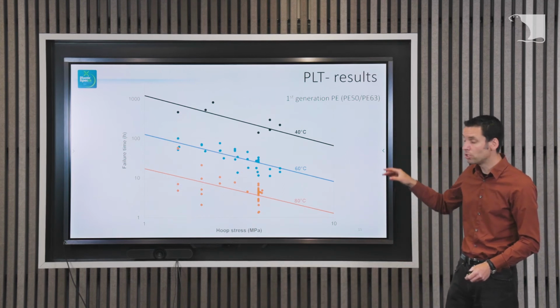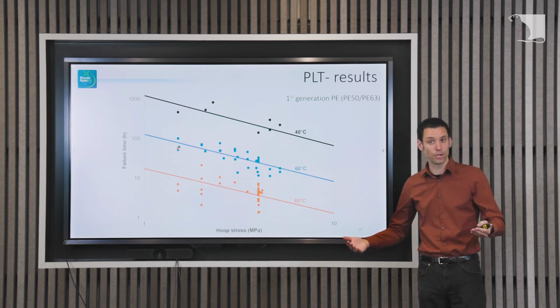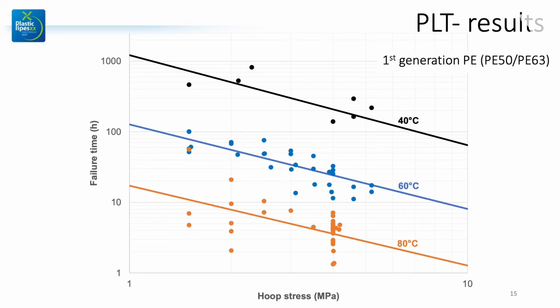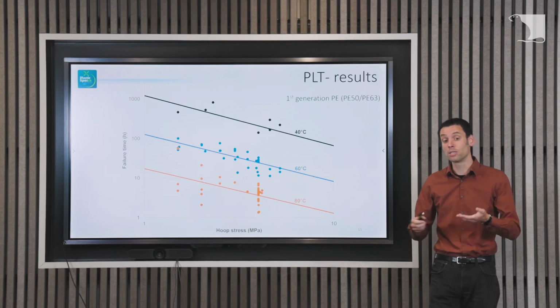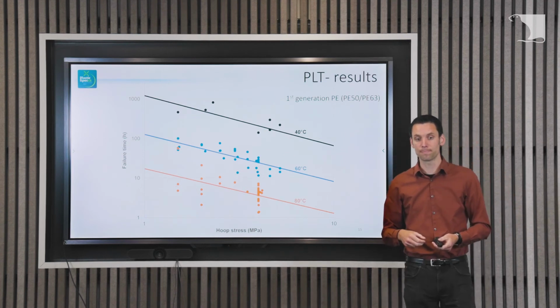What you see here is all those dots are those failure times of first generation polyethylene, but they're multiple polyethylene pipes from multiple locations in the Netherlands. Some were more used than the others. They have different SDR classes. We sometimes use different indentations for the point load. So we have different results here, but it still gives you a good idea, and you see really that there's a dependency on the hoop stress. So the internal pressure of those pipes gives rise to the failure time.